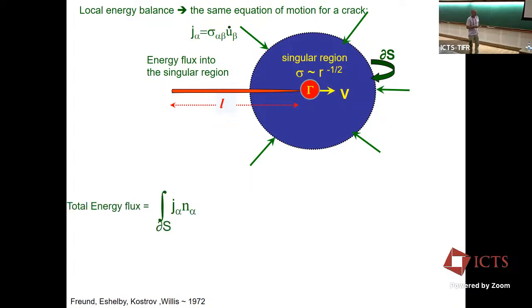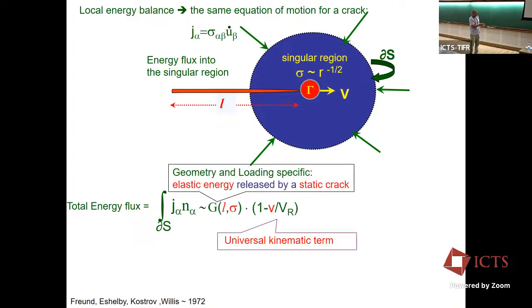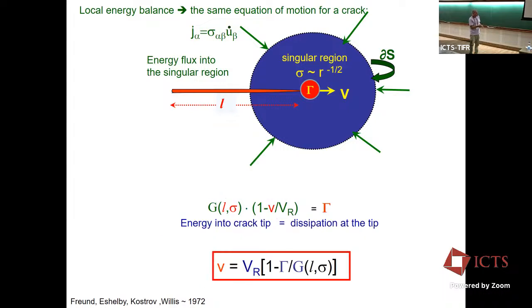But to do exactly the same thing is just looking at the flux of energy. Again, stress times strain, each goes like K over the square root of R. And when we do that, what you find is the same thing we just derived. So if you do it microscopically, and actually this talk does talk about microscopics in that sense, then you get the same equation of motion. That's what happens when you do it the way that most people do it.